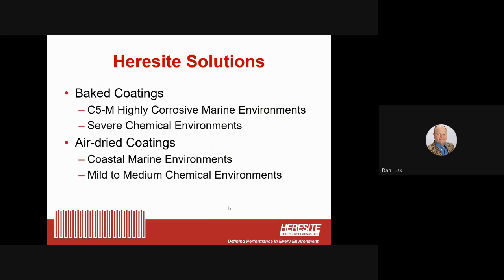So we have two basic types of solutions. And one is our baked coatings. This is coating that's applied and cured by baking in an oven. It's for the most difficult environments, both C5M offshore corrosive marine environments and severe chemical environments. These products are superior in performance to other products on the market. Our air dry coatings are spray applied, and they just dry in the air. And they are ideal for coastal marine environments and mild to medium chemical environments.